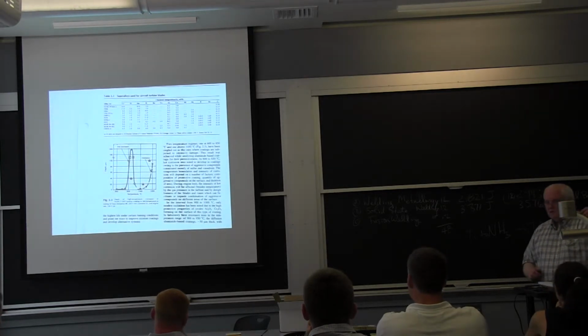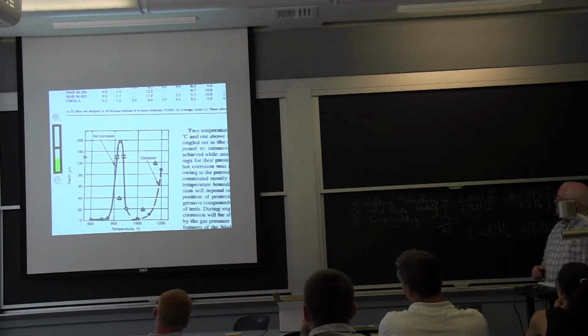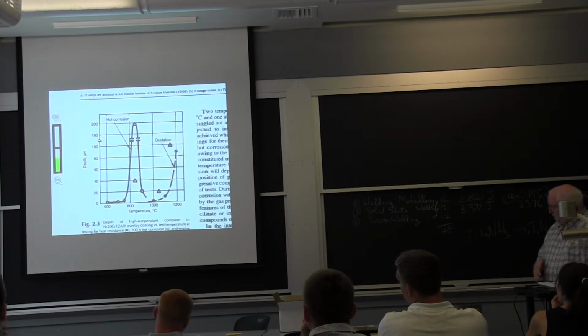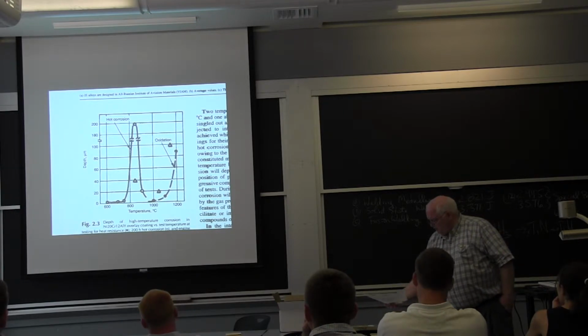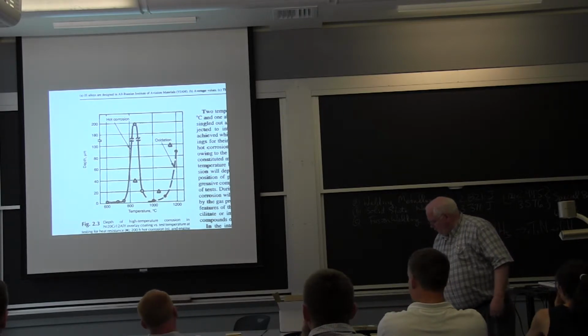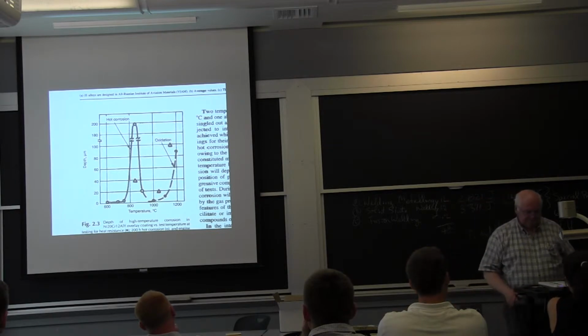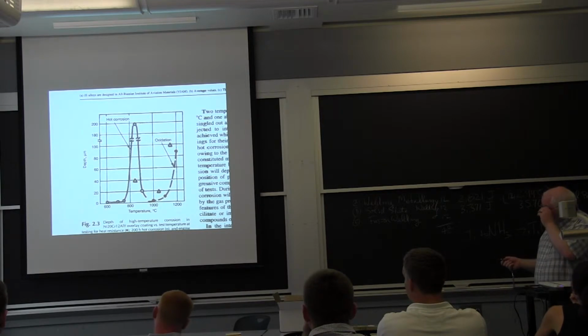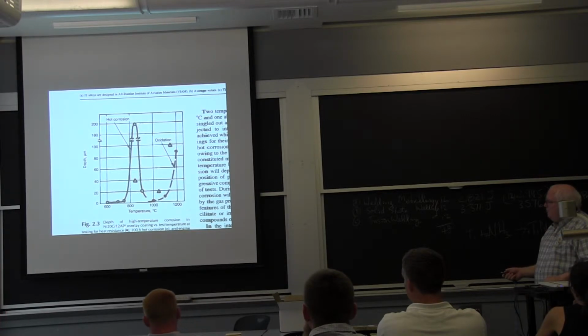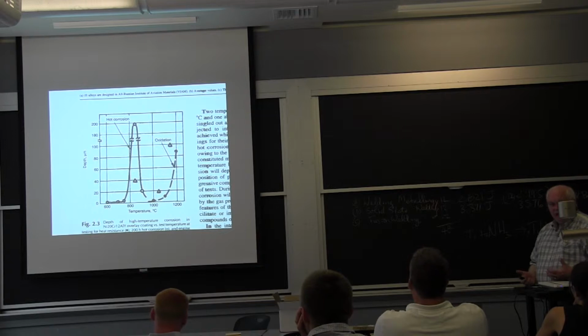that plane? So if you look at the sulfidation, the hot corrosion, and this is just giving you some idea of some things. The diagram explains the thermodynamics of corrosion, but the real problem in corrosion is trying to understand the kinetics, how fast it occurs. And this is for the high temperature corrosion of an overlay coating versus temperature for a nickel, chrome, aluminum, yttrium. We call it an overlay alloy.